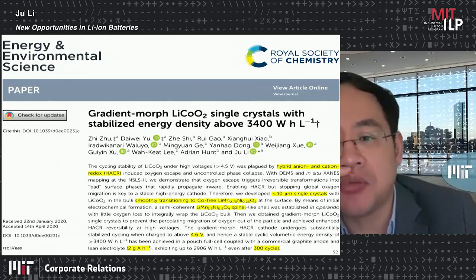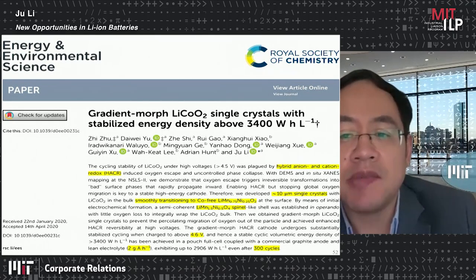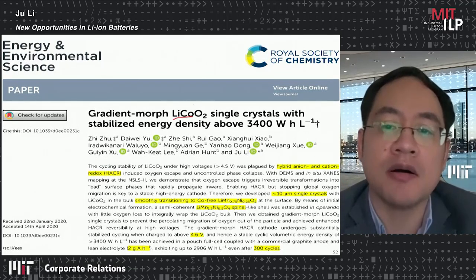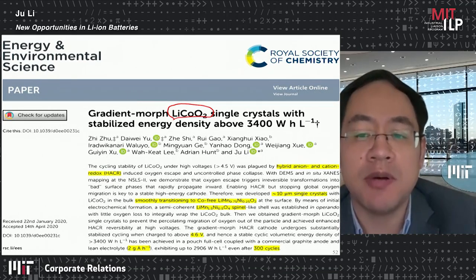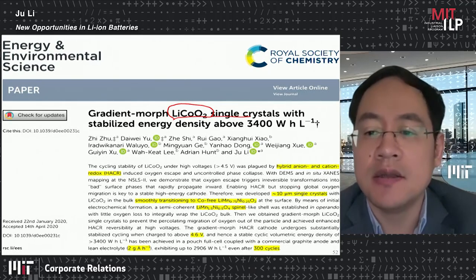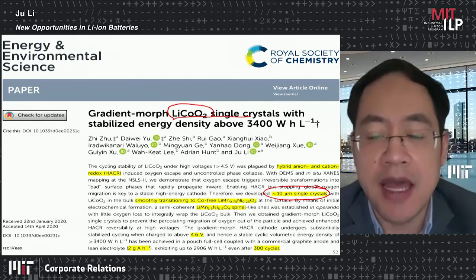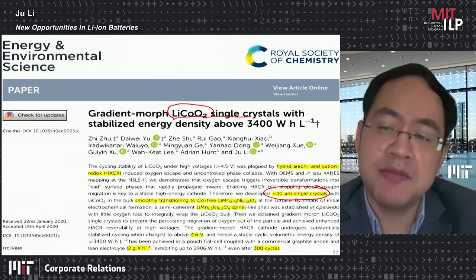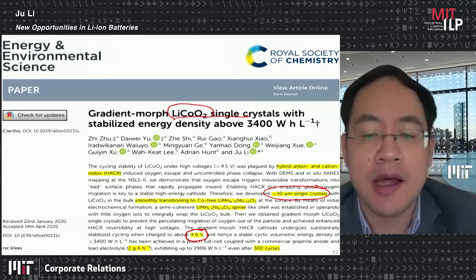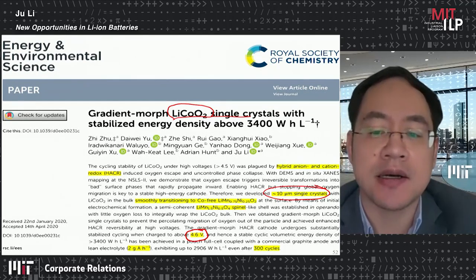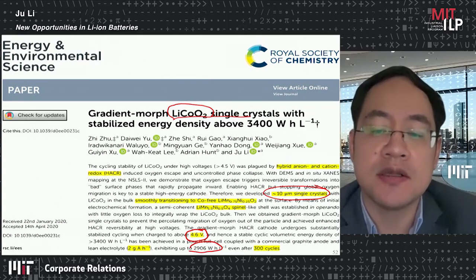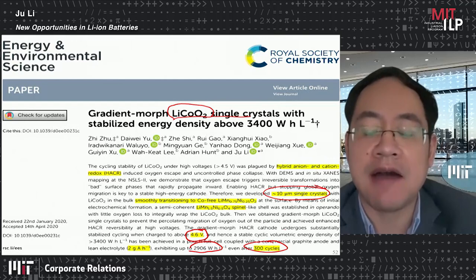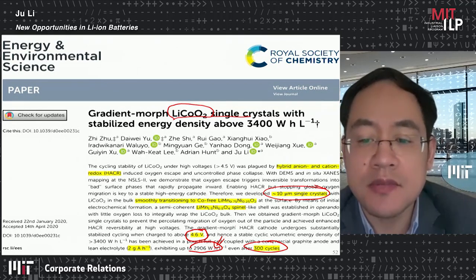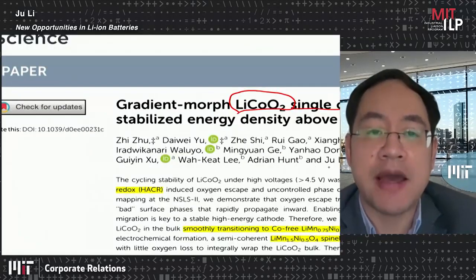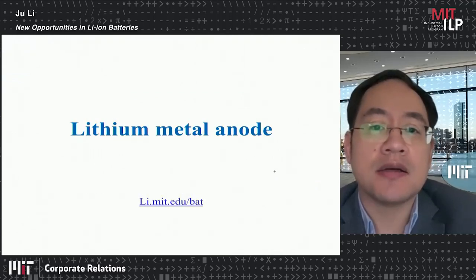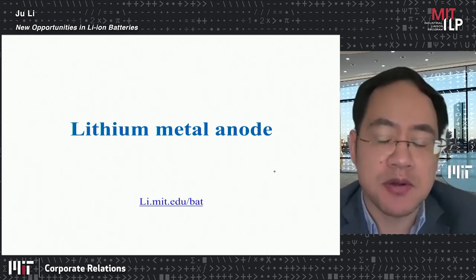And also using a similar gradient approach, we're able to also modify the surface of lithium cobalt oxide. In this case, we just use commercial lithium cobalt oxide single crystals. So these are 10 micron size commercial powders and single crystals. And we do a very simple gradient treatment, and we can charge up to 4.6 volt now. And it has about 3000 watt hour per liter cathode capacity even after 300 cycles. So this is the volumetric energy density. So those are the main things that we've done on the cathode side.